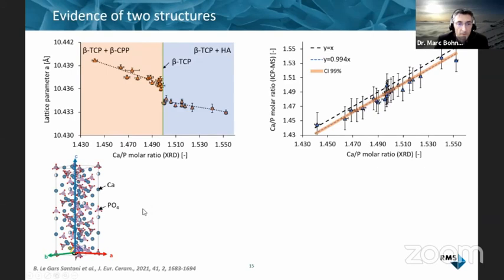Beta-TCP is a very special structure because it has 6 calcium 4 sites that are represented here in green. And these are half empty or half full. So you have 3 calcium that are distributed in these 6 sites. One of the assumptions is that this distribution is random, but there are also some atomistic simulations that suggest that maybe the filling is according to planes.